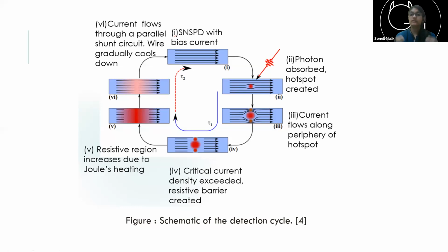These electrons will interact with phonons of the lattice of the superconductor and also the substrate. Ultimately, you want all of the heat to transfer to the substrate and down to the dilution fridge, right? So if the film is very thick, it could take longer. If you have an ideal SNSPD, it shouldn't take more than, I would say, 20, 30, 40 picoseconds for the dead time for very good SNSPDs. If your film is thicker, it could take up to a nanosecond, which means you'll miss a lot of photons. So in the dead time, this SNSPD cannot detect a photon.